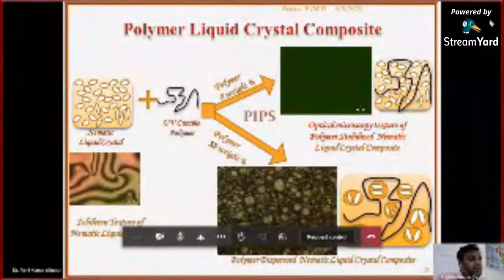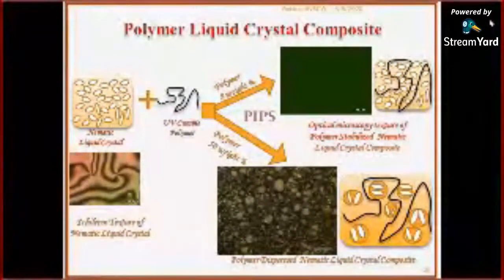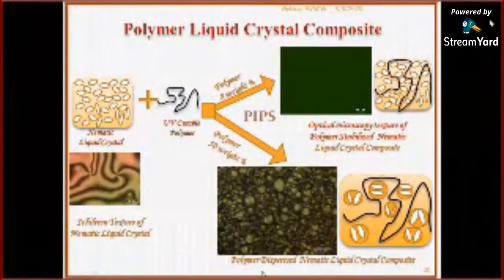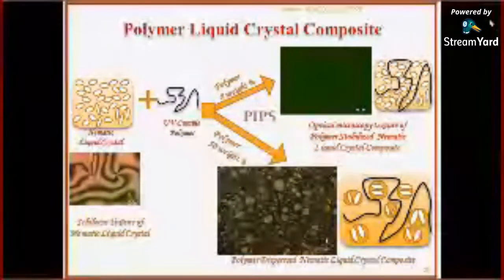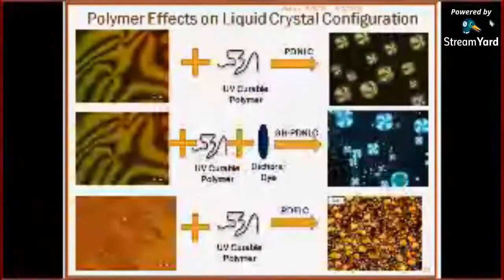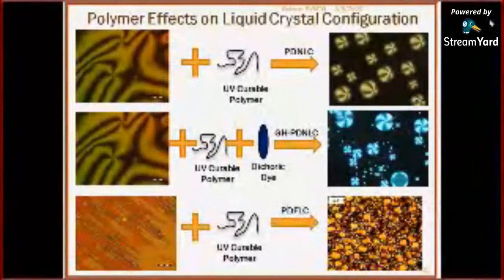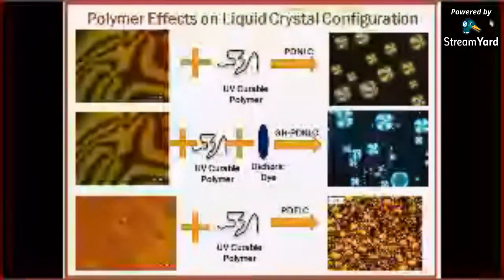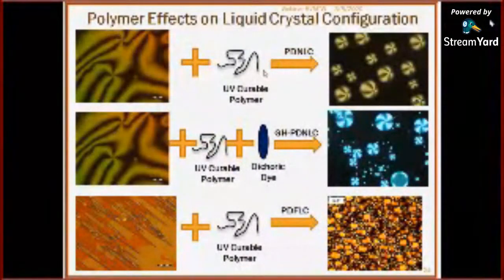So if we vary the polymer concentration, 50 weight% polymer and 50 weight% nematic liquid crystal, then we get this type of liquid crystal droplets, and that is the polymer dispersed nematic liquid crystal composite which forms, and this gives different types of display behavior. By using that type of UV curable polymer, we can see here the different types of droplets. These droplet behaviors give different types of response in electro-optic properties. Then we added some dichroic dye to increase the contrast of these droplets. So we achieved some contrast in these droplets.